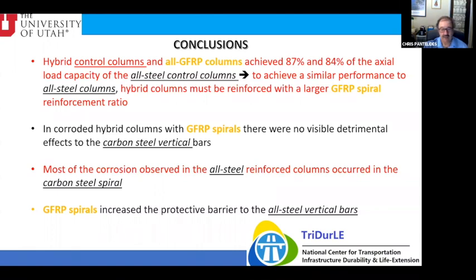It's a barrier, and then there's no byproduct. So the cover actually stays pretty intact, as I showed you in the picture. So there's no initial spalling. If there's no initial spalling, then the vertical bars are somewhat protected. Now, I can't say that it will happen like that for eternity, but at least for this accelerated corrosion test, which produced so much corrosion in the all carbon steel bars, it seems like it helped, at least for 11 weeks.